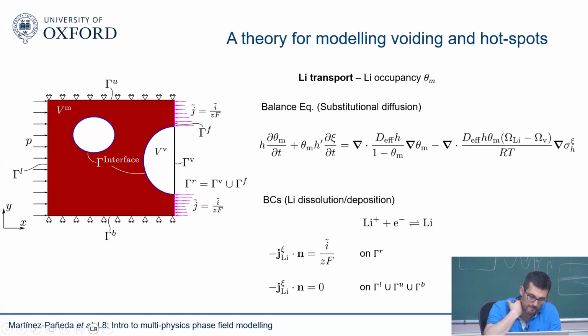Then what is important here is that you have a lithium transport equation to simulate the vacancy diffusion, and you have some interface reactions that will capture what's happening in the plating and the stripping, basically. So you change the sign, but basically you have this relationship, and we have enhanced this to account for Butler-Volmer as well, but it's the same idea.